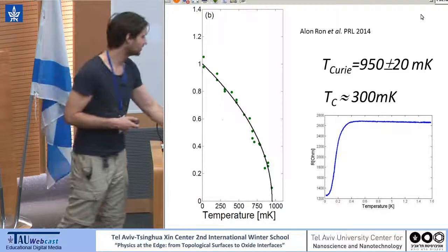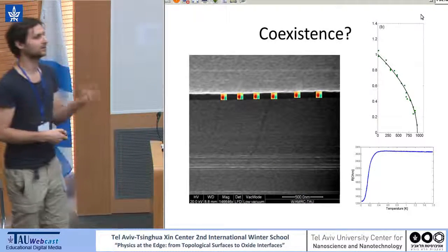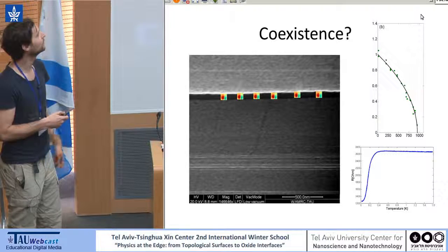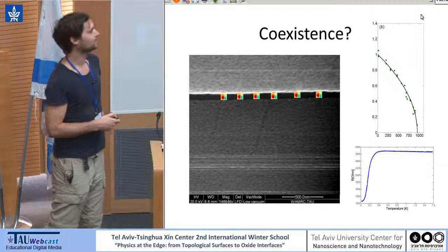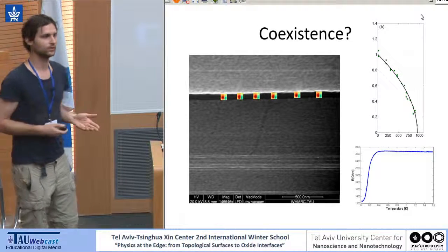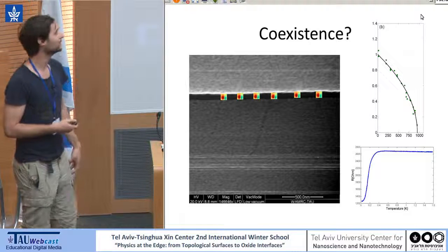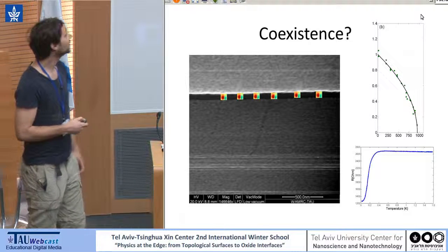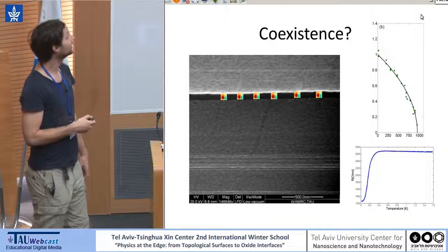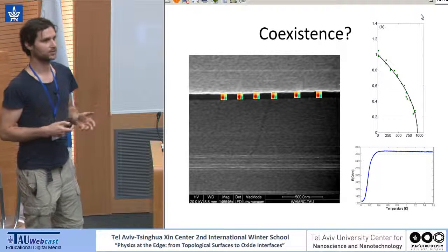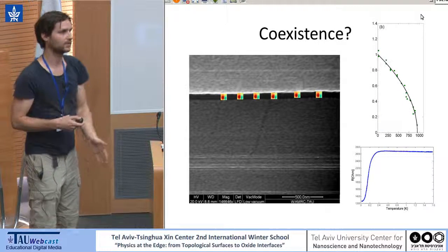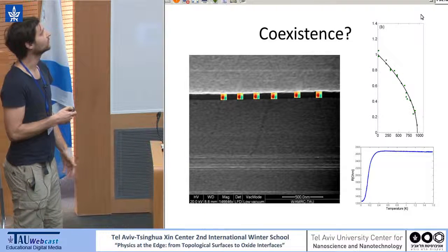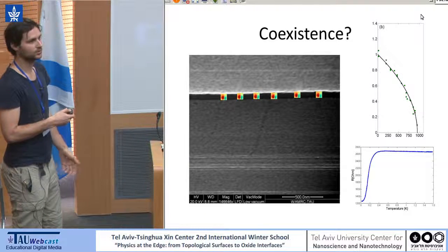At least my interpretation of this is, and I would like to thank Bina for those tiny dipoles, that we saw that the magnetism is not uniform in these films. Bina will maybe talk about it later this week. If the magnetism is not uniform, and now we force the current to go through a narrow constriction, we force it to go through those dipoles.